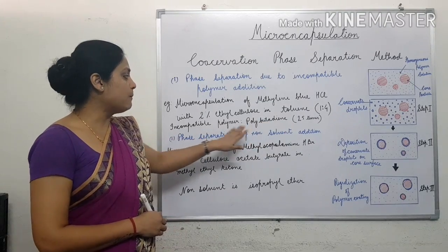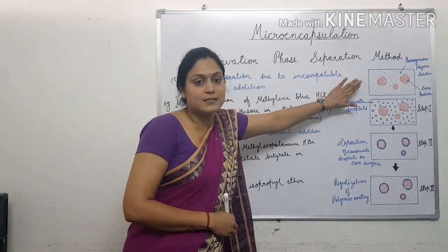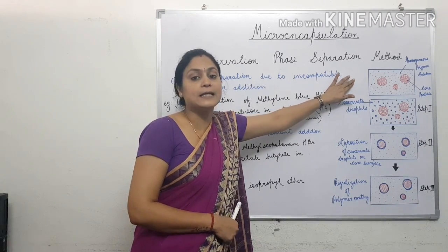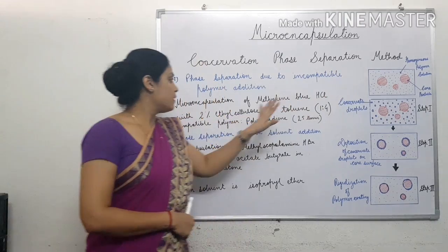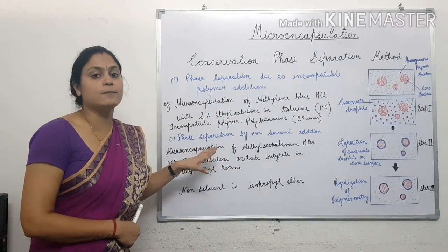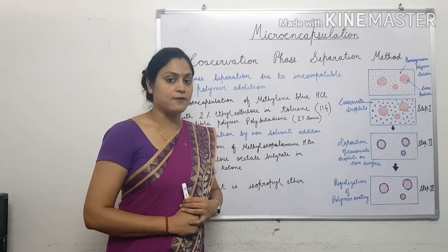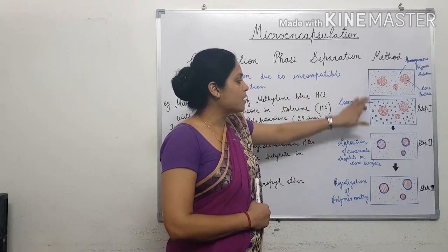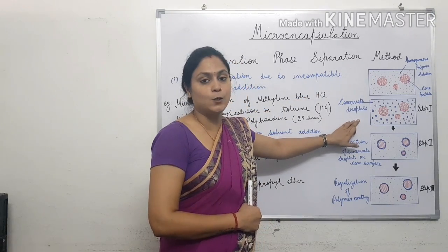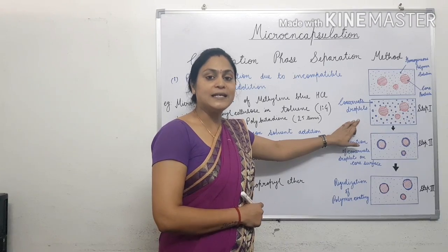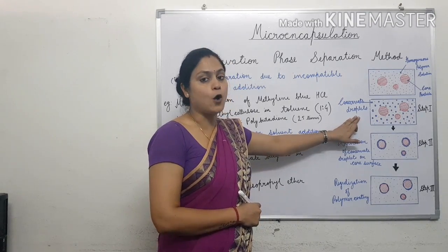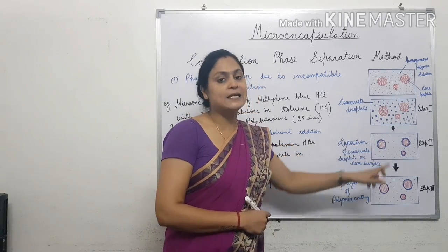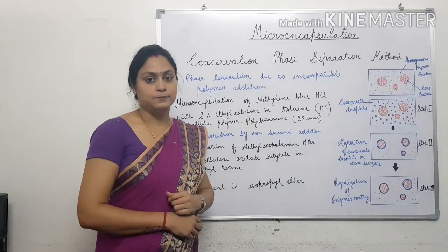When it is added in a ratio 2.5 times that of ethyl cellulose, a coating polymer to incompatible polymer ratio of 1:2.5, the coating polymer, ethyl cellulose, starts separating out as liquid droplets or coacervates, which start depositing over the methylene blue hydrochloride crystals.